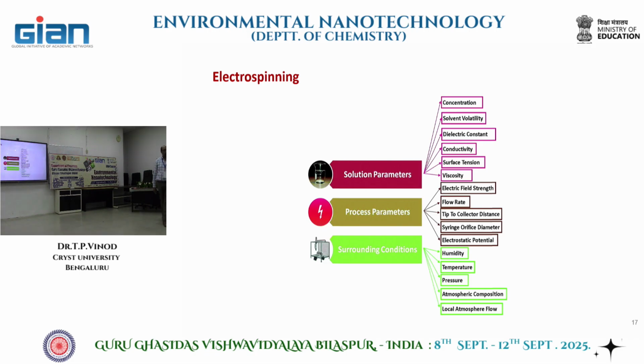But with certain polymers, suppose you want a conductive polymer nanofiber film, it may not be soluble in hexane or toluene. You may have to use some polar solvent also. And sometimes you may have to mix solvents so that you get an appropriate polarity for the process to happen. Then process parameters: electric field strength, how much voltage is applied; flow rate, with what speed the solution is pushed through the needle; tip-to-collector distance, how much distance there is between the tip and collector; syringe diameter, how big the opening of the syringe is; and electrostatic potential.